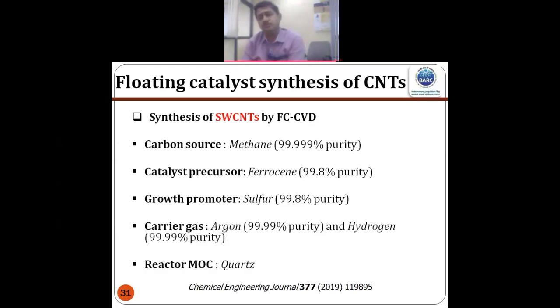We can also produce single wall carbon nanotube, but the technique slightly changes. That is called the floating catalyst method. In floating catalyst, we don't use any support material. Instead, the carbon source is taken as methane instead of acetylene, because with methane we can control the carbon easily. Then ferrocene is once again used, but we require another important material, sulfur, which is a growth promoter, as well as it controls the diameter of the carbon nanotube.